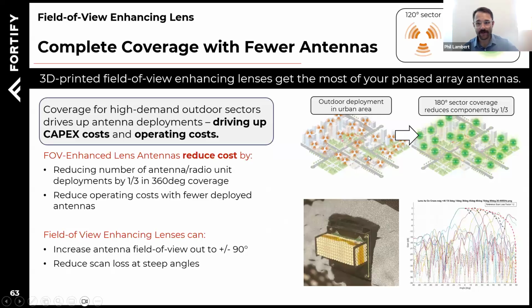Just want to quickly touch on how we apply this technology to phased arrays. Fortify and Rogers Corporation co-developed a field of view enhancing antenna. Sorry, I'm going a little bit faster because I'm running out of time. We developed a field of view enhancing antenna for a phased array. And this helps to achieve complete coverage over a region that you're trying to cover with a phased array with fewer antennas by increasing the field of view of an antenna from, say, 120 degree sectors to 180 degree sectors. You obviously need fewer antennas to cover the same amount of area.